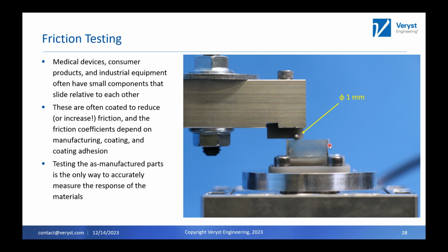Also, a lot of times it depends on the surface finish, so you want to make sure you test your as-manufactured parts with the molds you use. Sometimes there's post-processing, whether that's grinding, abrading, blasting, lubrication, plasma treatment, heat treatments. All those types of things can change your surface finish and then change your roughness. So in these cases, really the only way to do this is to test those manufactured parts against your surface that you need. So this shows an image of that.